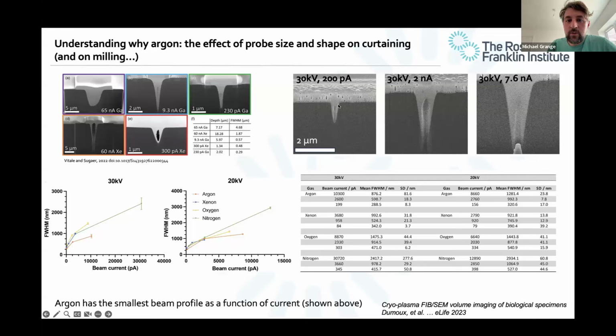So you have this Gaussian, and the shape of this Gaussian determines how flat you can mill for a defined period of time. And this full width half maximum was essentially the smallest for argon at low currents. And so that's what we assumed, that this is the nature of the probes that is causing the curtaining to be the least when we have argon.